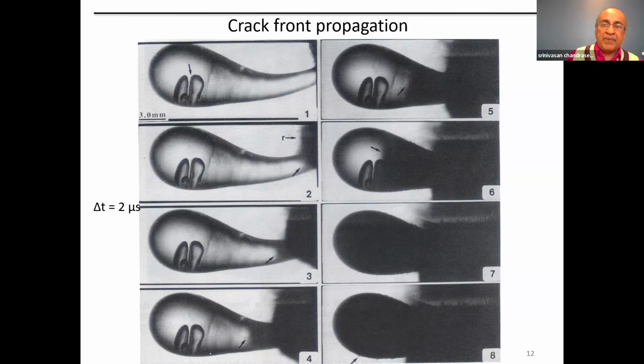So here is a picture of a drop. Again, you see the interior lit up in frame 1. This is before anything is happening. You see the vacuoles. What we are going to do now is trigger the explosion so that a crack starts propagating from the tail, which is on the right-hand side of the drop, and we're going to follow the sequence as to what happens to the interior of the drop. The sequence goes from 1 through 8. This is done at 500,000 frames per second, so between each frame, the time is 2 microseconds.